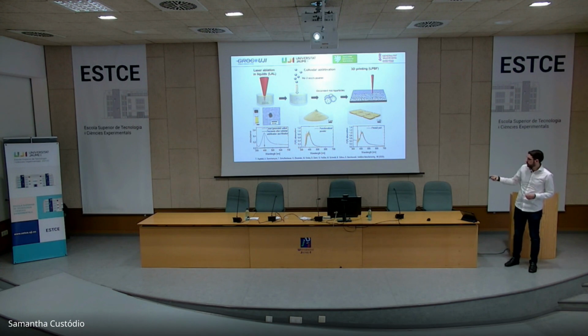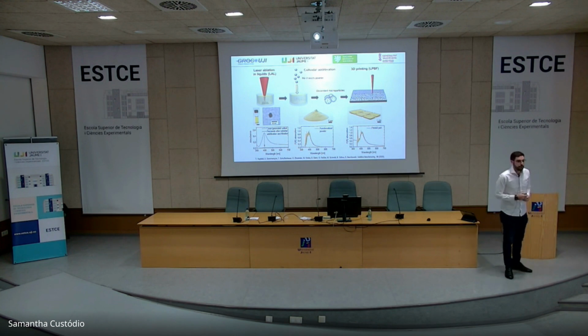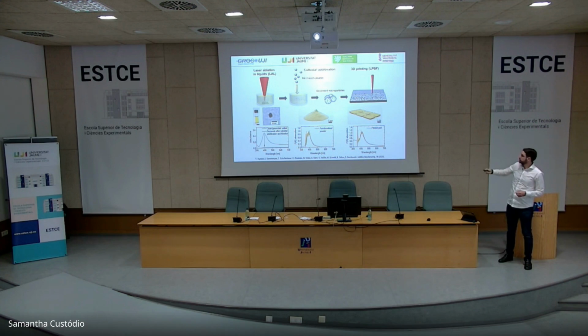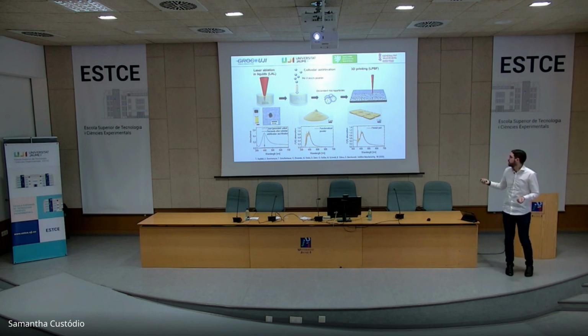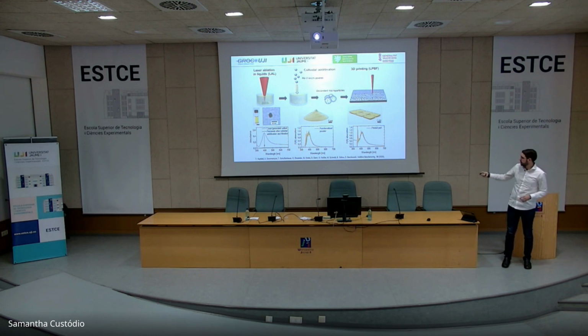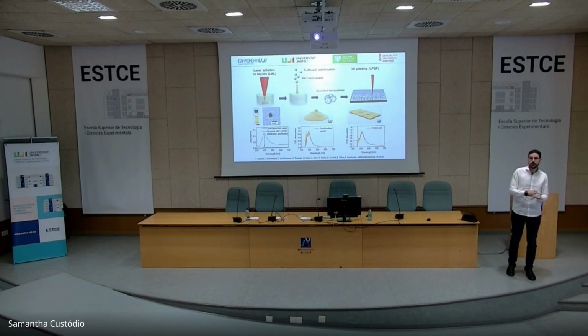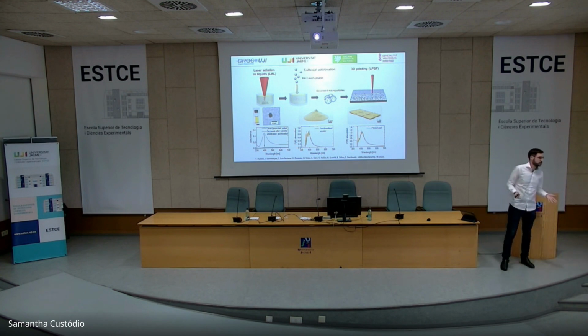And you see that we are able to transfer the plasmonic response of the initial silver to the powder that we are preparing. Afterwards, we print it with the laser. So we are just spreading the powder, and then the laser is basically melting or sintering the material, forming this solid structure that still keeps the same plasmonic response. Why is the plasmonic response interesting? Well, because as we have seen previously, if the size of the nanoparticles changes, then we will have a displacement of this peak. So this tells us that the nanoparticles keep approximately the same size as at the beginning of the process.